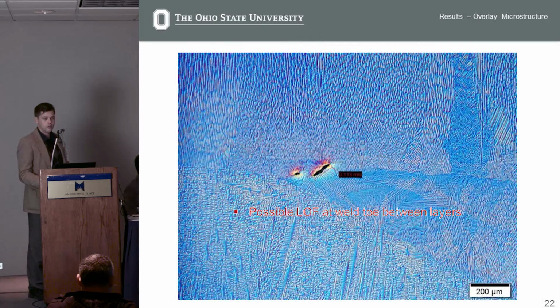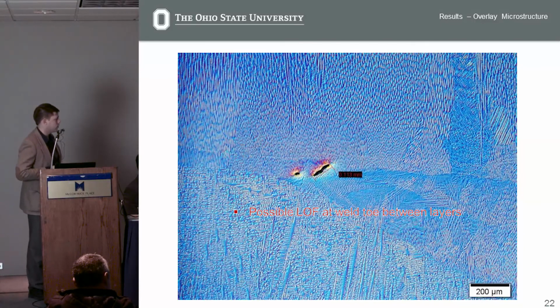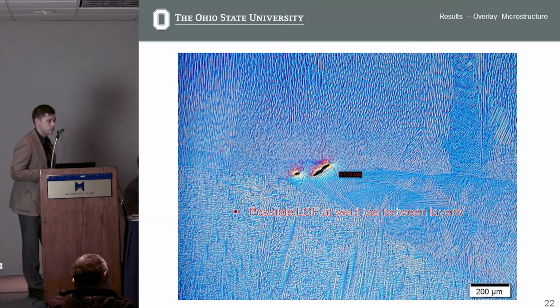A few defects were detected in this overlay in cross-section. This 113 micrometer long open discontinuity is possible lack of fusion at the toe region between layers. However, this is a defect that would be seen in even acceptable GTAW overlays, so it's not of paramount concern. It's also not detectable using current NDE techniques. Even with phased array, this might not be detected.